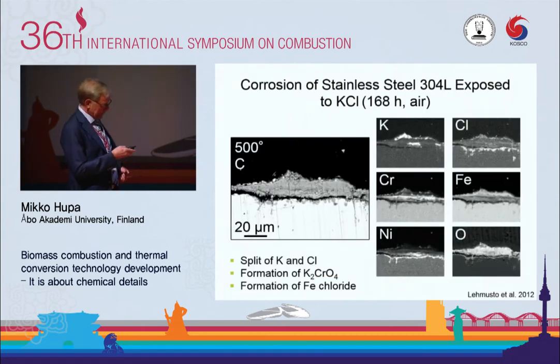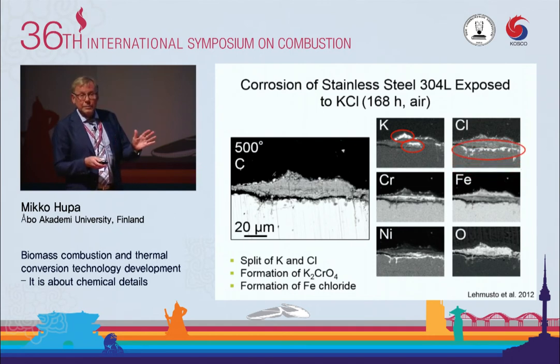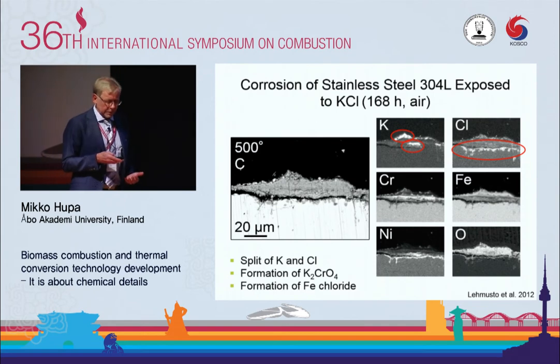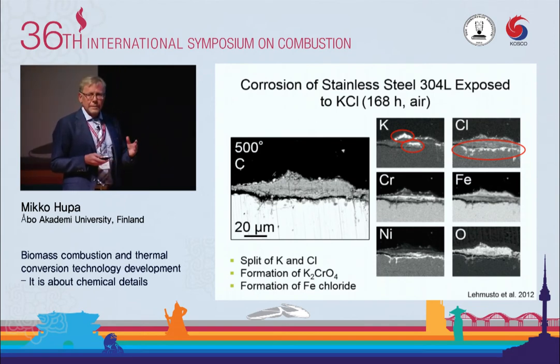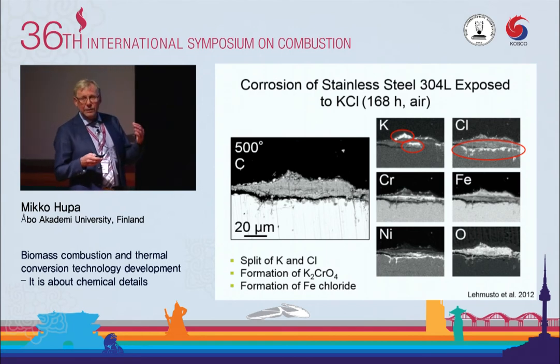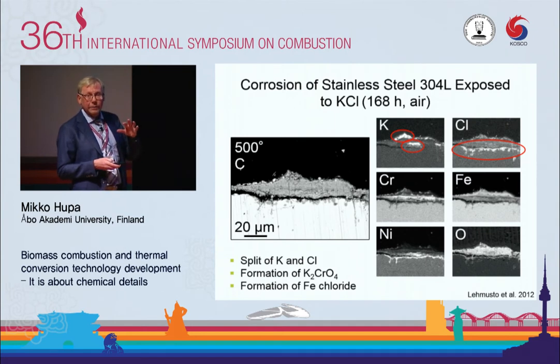I don't go deeper into this, but the key is that when we do this kind of microscopy, we can see that after a week of exposure, the potassium is still on the surface, but it is no longer together with chlorine. So there is a split of potassium chloride, but this is not because of the sulfur dioxide. It's just straight on the surface. And we know from many tests there is an interesting formation of potassium chromate, a chromium layer on the surface. And that chromate formation has not really been so well reported before. Now it is a really interesting thing. And under which conditions does the chromate form? It doesn't last long. It's just an intermediate which breaks the surface.